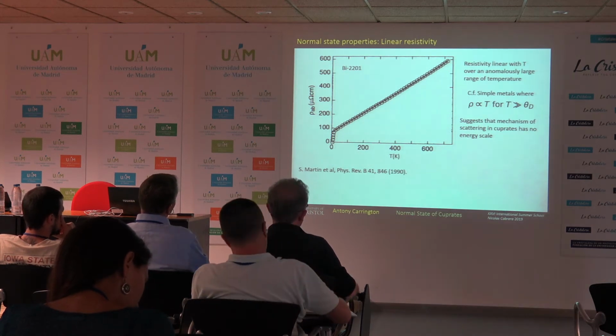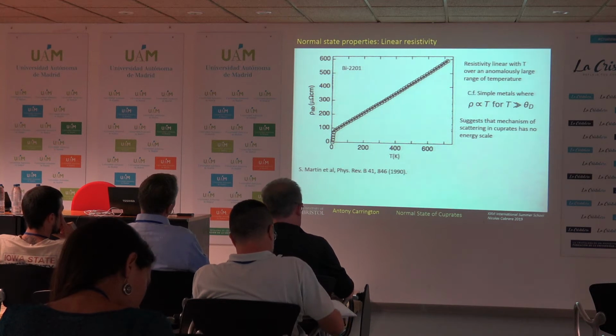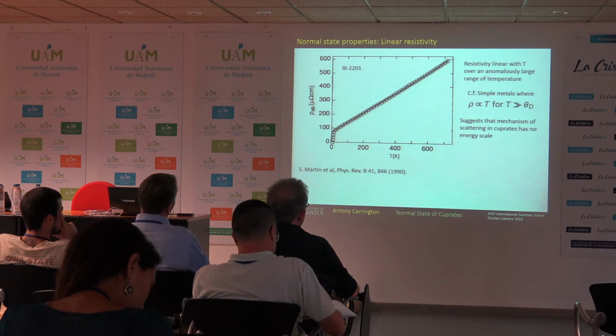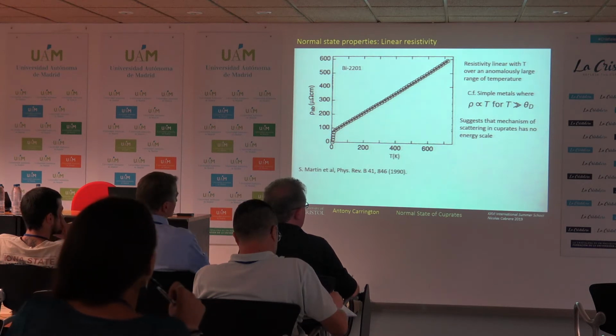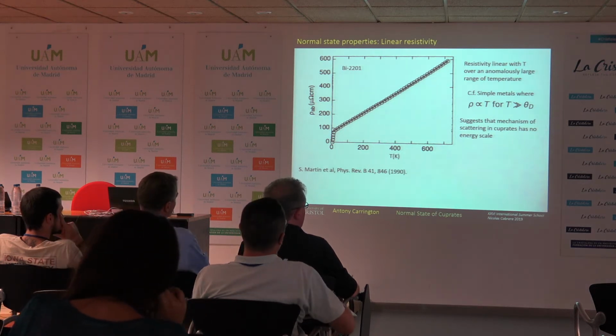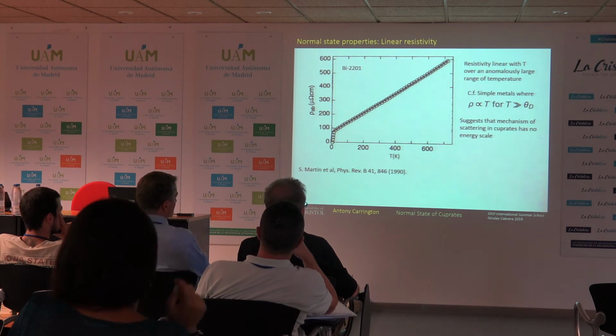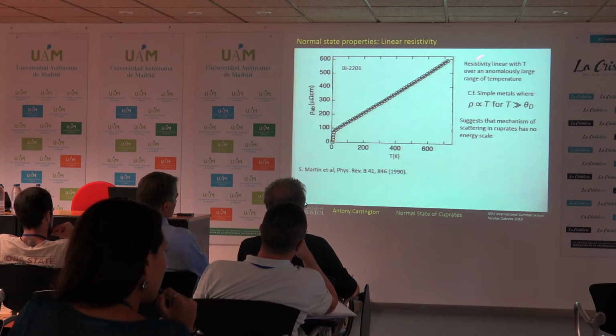So what do we mean? So we all know that if you take a normal metal, at sufficiently high temperature, the resistivity does vary linearly with temperature, right? Otherwise you wouldn't have platinum-based thermometers, for example. They'd be useless, right? But the point is that in the cuprates, this linearity extends over an extraordinarily wide range.